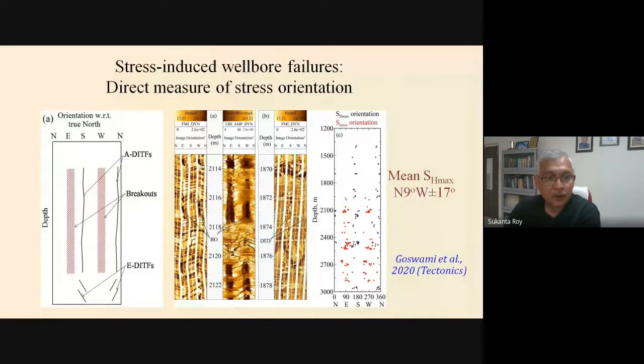Then we looked at the borehole breakouts and the drilling induced tensile fractures from the image logs. And you can see on the right hand panel here, we plotted the SH max orientation as well as the SH min orientation, which is obtained from the drilling induced tensile fractures. And we were able to get a mean SH max of north 9° west.